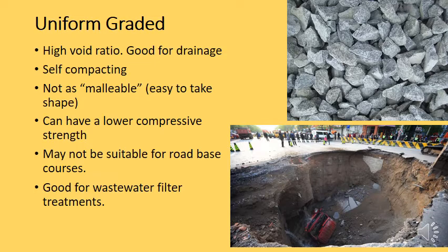So an advantage of this is if you have a big hole in the ground that you need to fill. This picture in the bottom right is a sinkhole that emerged in Japan. What are you going to do to fix that hole? Obviously you need to fill it in with an aggregate, and then you can build the road surface again. But you can't fill it with a well-graded aggregate, because then you would need to compact it, and there's no way you can get a roller down there to press it and compact it. But if you filled it with a uniformly graded material, it would just fill up like marbles in a bucket, and you won't need to compact it. It will be self-compacting. Then on the surface you can place a well-graded aggregate to give strength for the road, and then you can put your asphalt surface down.